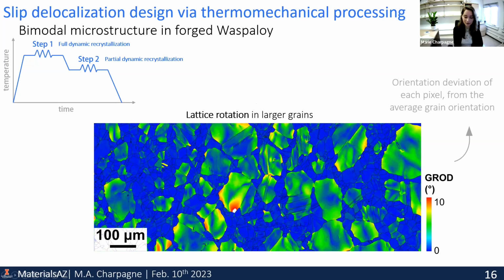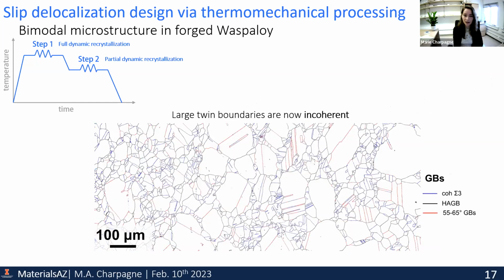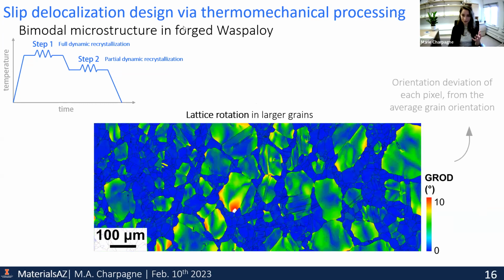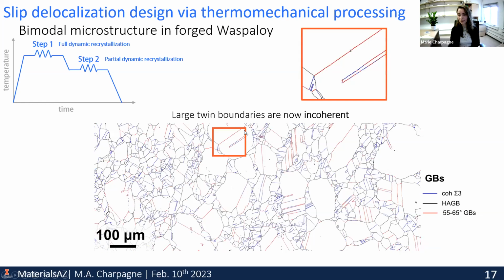So this is another characteristic of those grains. And then looking at what we really are after, meaning the twin boundaries. So we see that in those large grains, of course, we have twin boundaries that formed during step 1, dynamic recrystallization. However, in the second step, they are very distorted because of these lattice rotations that were added. And so we're looking into how that has affected the coherency of those twin boundaries, because, just reminding you, we want to get rid of the large and coherent twin boundaries.